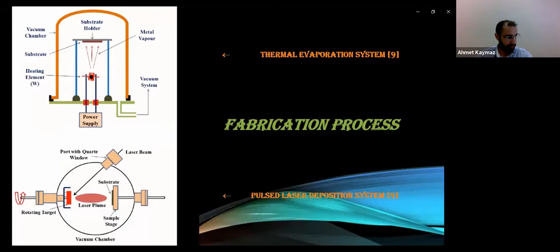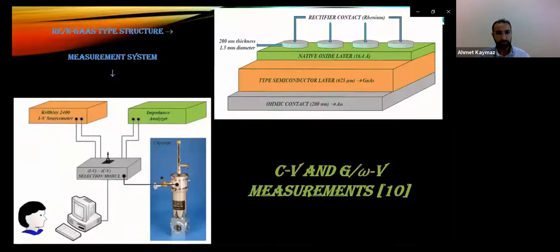And then rhenium with 99.9% purity was coated onto the front side of the substrate using the pulsed laser deposition technique. So, the fabrication process of the rhenium and gallium arsenide type Schottky structure with a native oxide layer was completed and ready to perform CV measurements. A three-dimensional representation of the MS-type Schottky structure that we have produced can be seen in the figure.